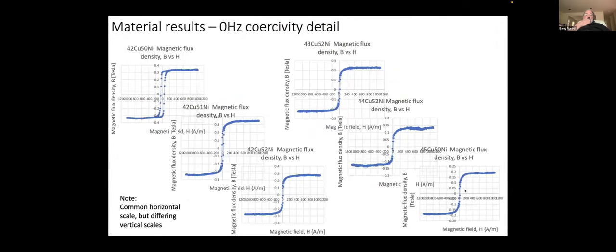Okay, onto these actual BH loops. So up here, this is the 42% one, which had that relatively poor initial permeability. It's actually a permanent magnet if you look at its curves. It's very square. None of the rounded curves that I expect on a low noise material. So this one has clearly gone into that segregation area that I was talking about earlier.